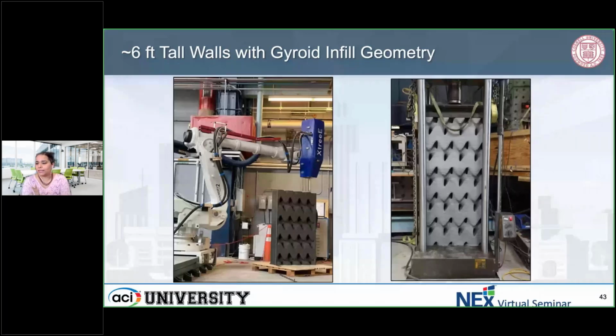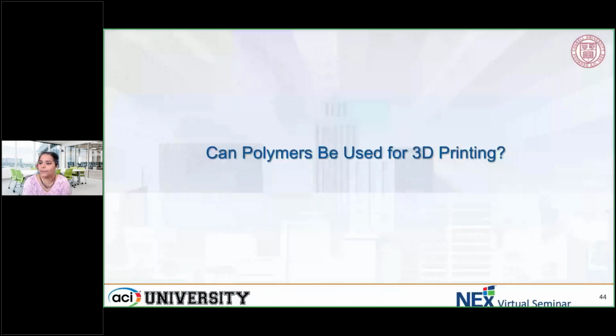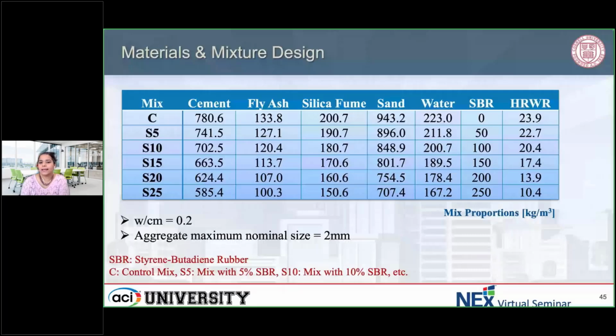But in the remaining 10 minutes or so that we have, the final thing that I want to talk about is how we can use polymers for 3D printing, right? So we did a small study when Monique was a postdoc over here in my group, where we replaced the cementitious part with SBR, which is styrene-butadiene rubber latex, in different proportions. So S5 would be 5% SBR in the mixture.